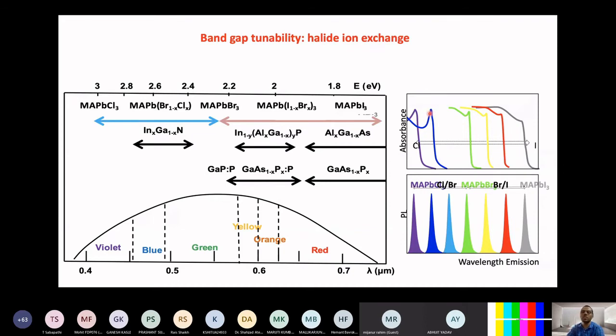If a semiconductor is excitonic in nature, you will not get your absorption following the density of states formula of 3D semiconductors, where density of states is directly proportional to E to the power half, and that would make one parabola. But instead of making the parabola, there is an additional peak, and then you have this E to the power half increase. So this is with respect to wavelength, this is lambda here. This is shorter wavelength. This is higher wavelength. But if I plot this graph on the energy scale, then you'll find that this will follow the E to the power half relation beyond this excitonic peak. But the excitonic peak becomes dominating as we go from iodine to bromine and further to chlorine.